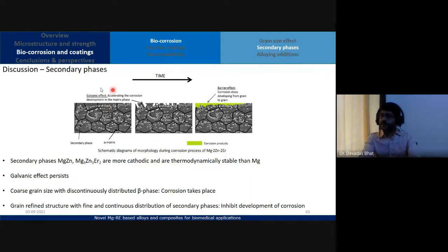Also, when we discuss what we call the galvanic effect, as you all know, if you have a difference in the corrosion potential or electrochemical potential of the two elements, galvanic corrosion takes place. So our secondary phases were more stable than the pure magnesium. But if they are uniformly distributed and fine in size, then we can have what is called the barrier effect. That is nothing but the corrosion will stop developing from grain to grain.